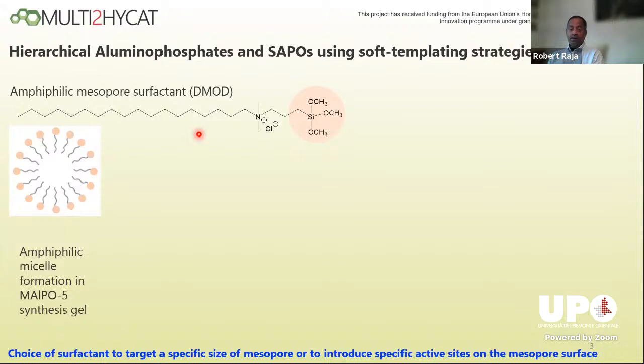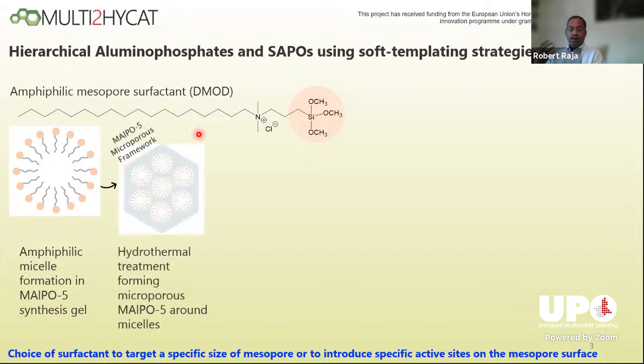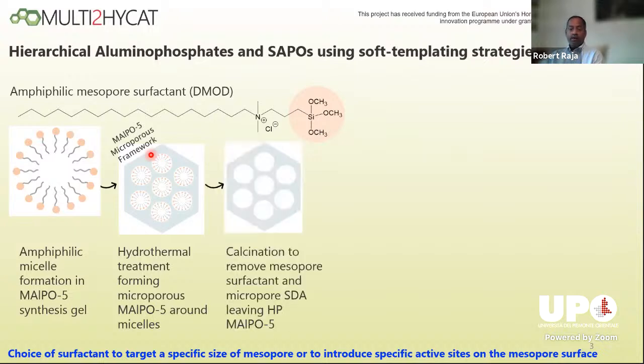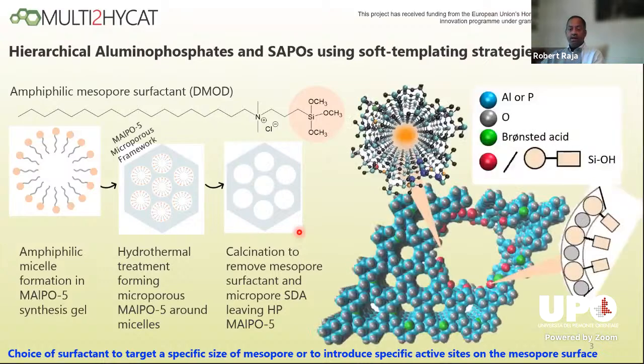As part of this project, we were looking at fine chemical and pharmaceutical applications, and this entails inherently using bulky starting materials. So having these hierarchical motifs would be quite useful in terms of looking at applications which can happen in the vicinity of an active site within a confined pore aperture, but having still the enhanced diffusion and mass transport. So the procedure is very similar to how you make zeolites or zeotypes. And then you form the secondary porosity within the confines of this microporous cavity or channel. And when you calcine, you can remove this surfactant molecule to leave micropores which are interconnected with mesopores, as you can see there.